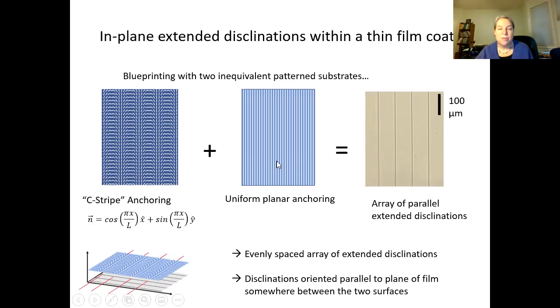If you put one of these on top of one of these, some magic happens, and the liquid crystal in between forms an array of parallel, extended, identical disclinations. This is not a defect structure that can occur with dislocations in crystals. If you have equivalent defects, the energy explodes in crystalline solids. But in this soft matter material, with this anchoring, we can, and these are +1/2 defects, they can all be identical, and you get an evenly spaced array of extended disclinations. For experts in the audience like Chuck Rosenblatt, I will say that's because there is escape in the 3rd dimension, and we've done some work with Chuck to understand the nature of disclinations in liquid crystals.